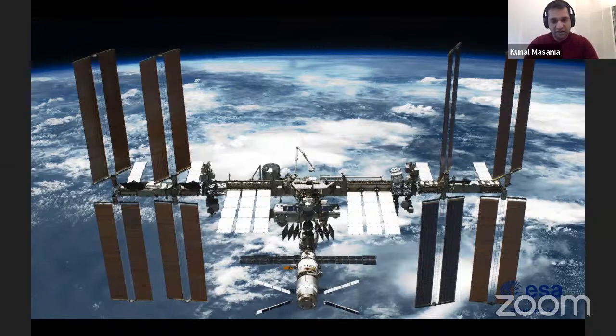So for me, it's really insane, and it's the perfect example of circular material, because anything you send to space has to be reused and used again. And so it's an opportunity where we can, in the future, maybe 3D print things, and then at end of life, we can chop them down, reproduce filaments, and reprint new structures. And from the early experiments we've done, we found that up to 5 times recycling, you don't really lose any mechanical properties from the material, which is really, really nice.